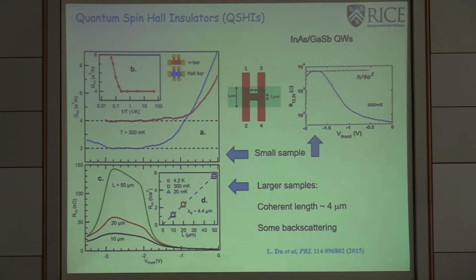So that's what one can observe. So this looks all fine. This looks like some kind of a proof for the quantum spin Hall effect. But if you make the sample bigger, much bigger than this typical size of 2 micron, then you end up with non-quantized edge transport. So this edge actually became ohmic. So you have a 10 micron, 20 micron, 50 micron length, and the resistance is actually proportional to the length.